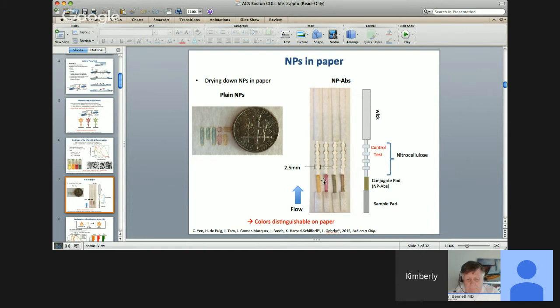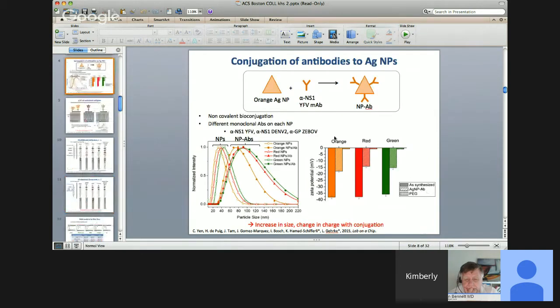Okay, and so these are four different lateral flow strips that we've made, and you can see that this is orange because it has the orange nanoparticles inside it with the antibodies. The red ones are here, the green ones here, and this is a mixture of all four, so it looks brown. So you can see that the colors are easily distinguishable on the paper as well. Okay, this is about 2.5 millimeters wide, just to give you a sense.